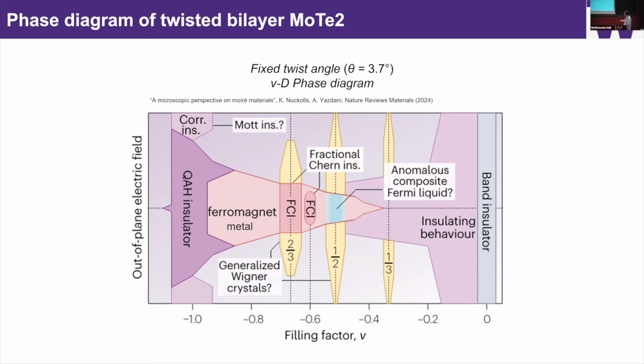Then at filling factor -1/2 near zero electric field, there can be an anomalous composite Fermi liquid, or CFL, state at zero magnetic field. The application of electric field will drive it into some kind of charge-ordered state. Then below filling factor of -1, what we see is all charge-ordered insulator states, which are topologically trivial.